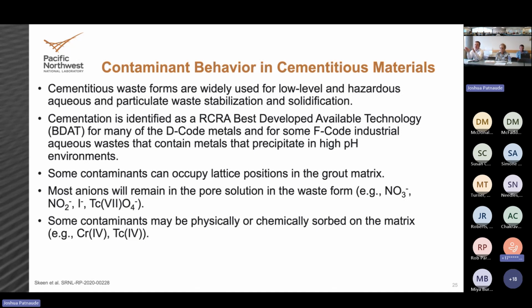In some cases, in some grouts, we can get those contaminants to go into the mineral structure of the grout as those hydration products are growing outwards. In other cases, they'll precipitate as just discrete products that we can go in and see on the microscope. And other elements, maybe ones that we're not as concerned with or ones that are more challenging, will just exist as salts in that pore volume. Things like nitrate and nitrite, harder to get into the matrix of a grout, so they'll mainly sit in that pore space, and then their release becomes dictated by the rate of water movement in and out.